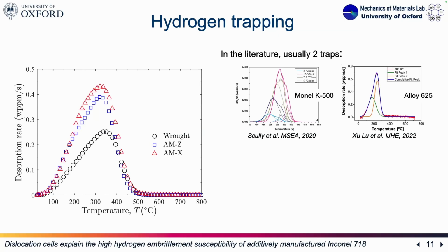I had to decide, and that's something you have to decide, how many traps you want to fit, or how many traps you have in your material. This is always a tough decision because we know there can be many traps with very close binding energies. But I checked the literature. Usually for nickel-based alloys, people consider 2 or 3 traps. So for the sake of simplicity, I said, okay, I'm going to consider 2 traps.